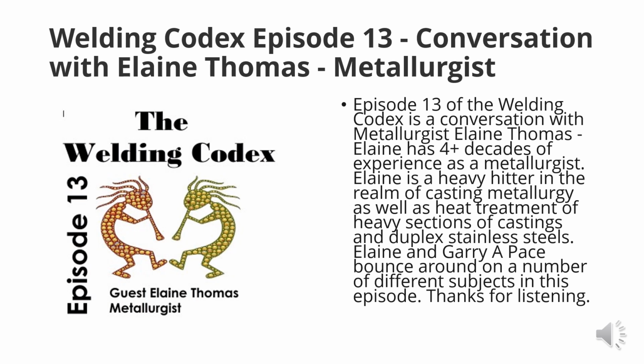When I started with Elaine, I just thought castings came perfect. I didn't realize that when you get a casting and you break it out of the mold and chop off the risers, there's going to be some repair work needed. So usually when you're getting a casting, there's been hours and hours of welding put into it. There might be porosity or cracks, or the metal didn't go where it was supposed to inside of there. So you spend a lot of time grinding, air arcing, cleaning up these castings, and then putting metal back in. That's what she's talking about with this post-weld heat treatment, where you send it back over to the heat treat people. They take it up to the 2075 and then do whatever in the post-weld heat treatment zone. And then you clean up the casting and send it on.